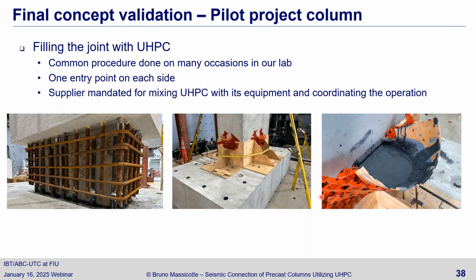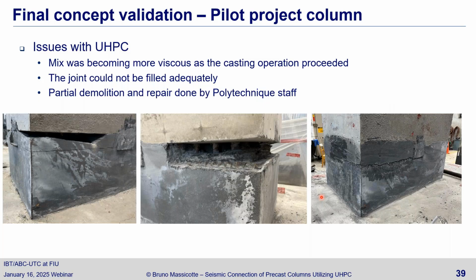And we asked a UHPC supplier to come and use its equipment and its personnel to do the job. It didn't go very well, actually. It was probably too hot that day in our lab, and it was during summertime. It could be very hot in Montreal during summertime. So the mix was becoming more viscous as the casting proceeded, and at the end we were not able to fill the specimen. So we were quite sad at the university, but on the bridge engineer side, I would say it's good that things don't always go well.